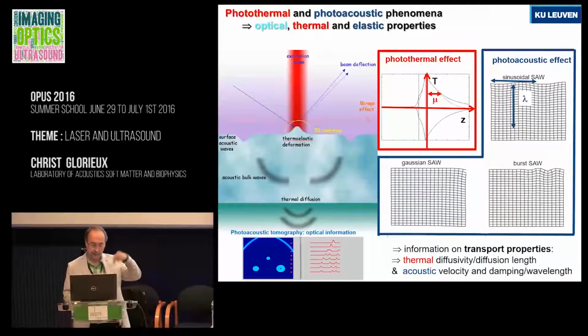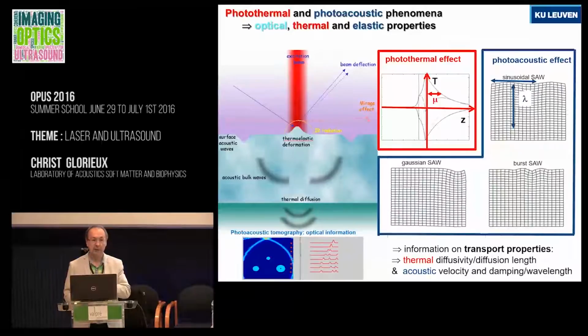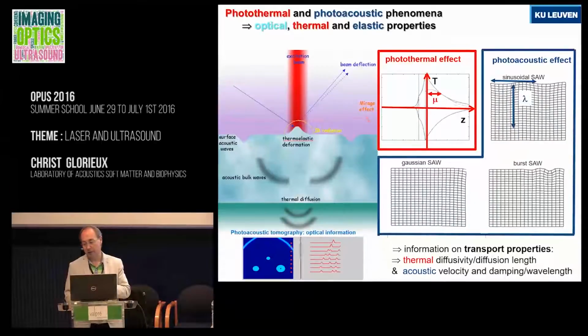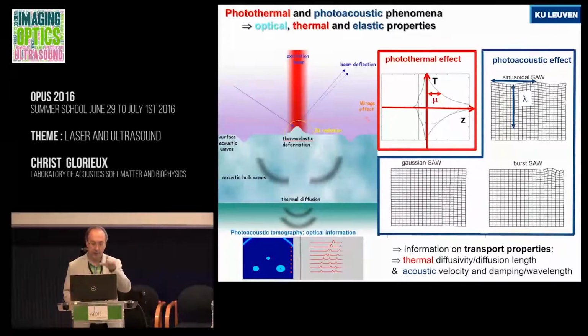Yeah? They don't go very deep, but they still go a little bit deep. And the depth that they penetrate is actually quite similar to their wavelength. As you can see, the wavelength is about the size of the lateral size of this sample here, and the depth of penetration, so until where it stops, is about the same. So you can use the wavelength, and if you think about waves, wavelength is related to frequency. You can use wavelength or frequency to play with the probed region, yeah?